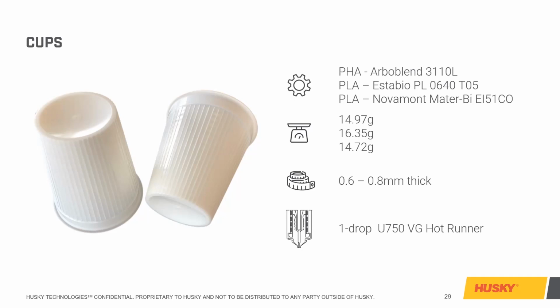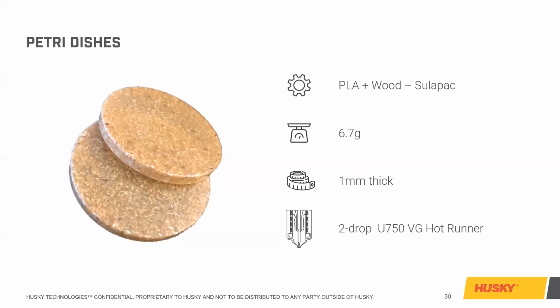We do resin trials, as I mentioned, in our lab, specifically for resins that we haven't encountered before. We have several test tools that we use. One of them is a Petri dish tool, and we ran this specific resin on this 2-cavity Petri dish tool at Husky. It's a PLA plus wood. It wasn't cellulose, it wasn't wood pulp, it was just wood chips that were mixed into the PLA.